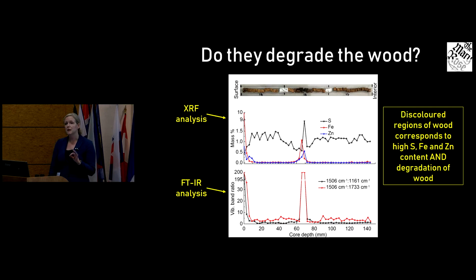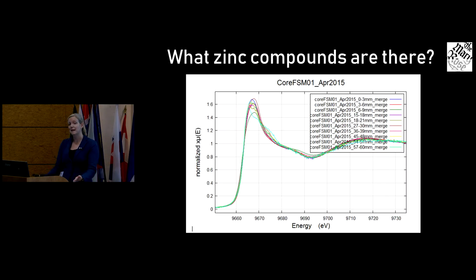So FTIR is really powerful with the wood because you can look where it's degraded, because you can distinguish the lignin from the hemicellulose and cellulose. And the latter two are the ones that degrade preferentially. So you see a much higher proportion of lignin where it's really degraded. And sure enough here, you can see the core at the top, you see where it's darker. This matches with where it's more degraded, where there's sulfur and iron, but also where there's zinc. So this is another kind of indicator that zinc is playing a role in this. So this took us back to the beamline.